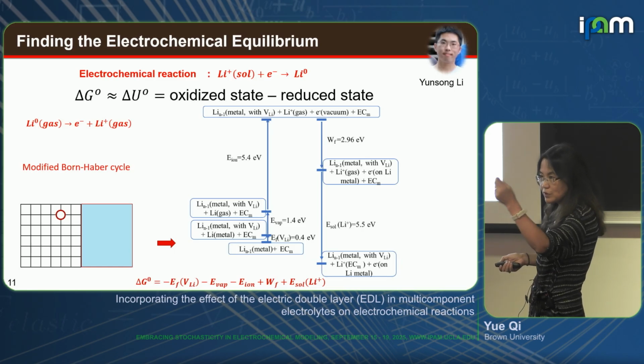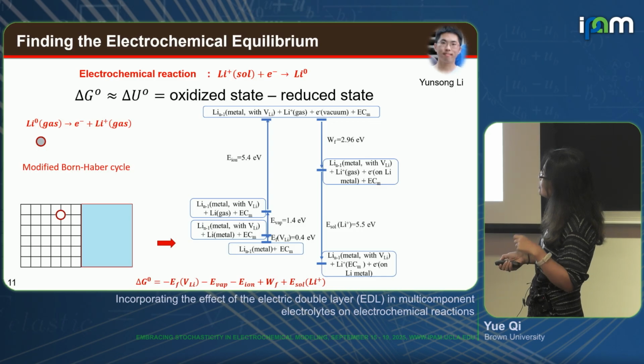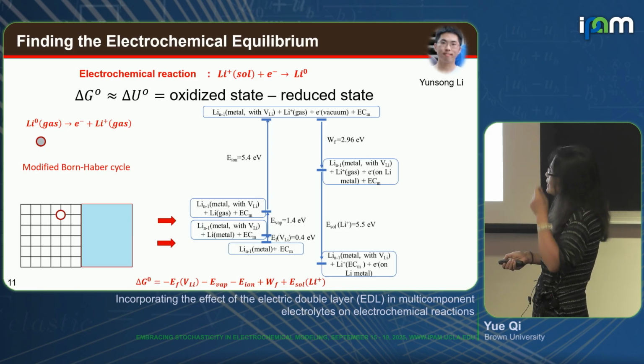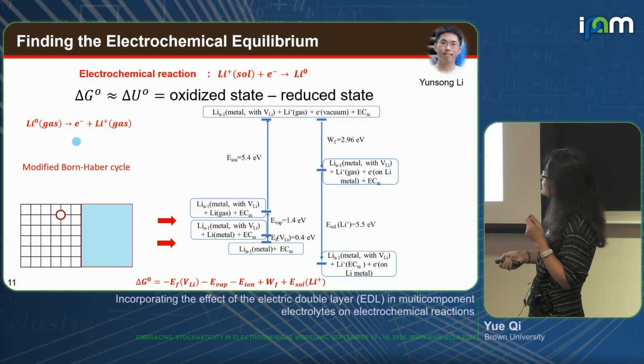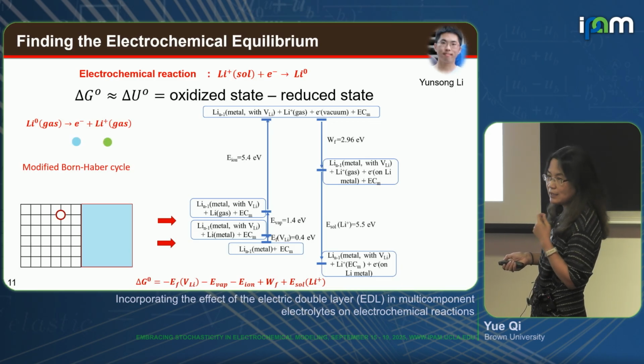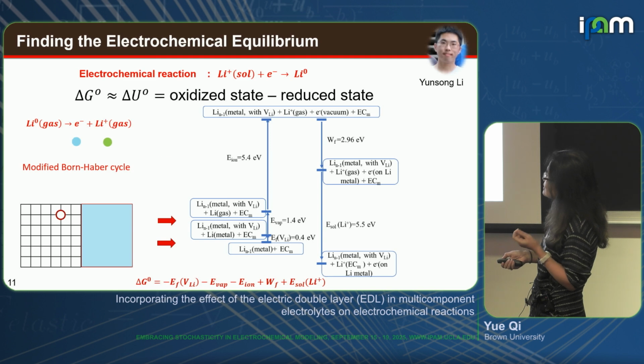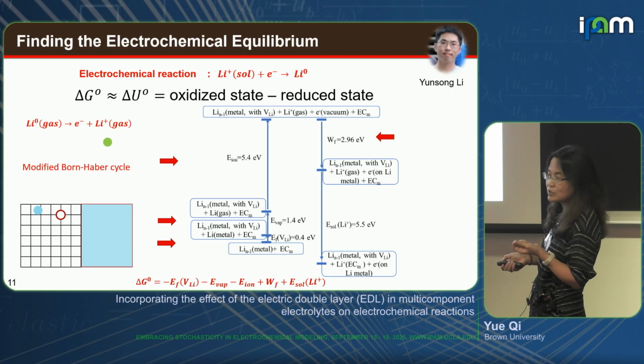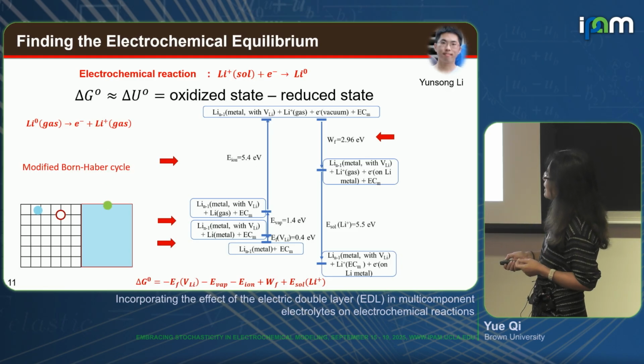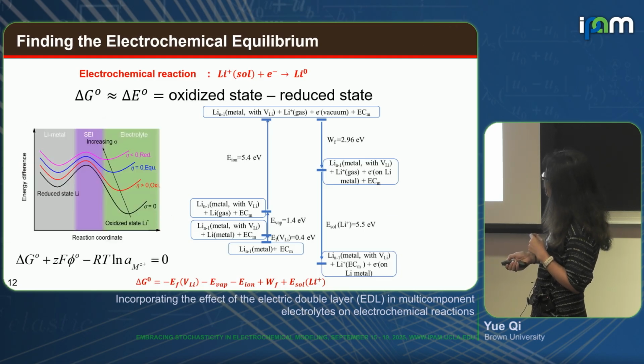And material science typically put that atom back to the bulk. So here we're going to take this atom to the gas phase, and then we're going to split this electron from the ion, and that's the ionization voltage. Then we're going to put the electron back, and that's the reverse of the work function of the lithium metal. Then I put the lithium in the solvent, and that's solvation energy. After this, we can see that in this charge neutral status, this lithium ion is very energetically stable inside the electrolyte, right?